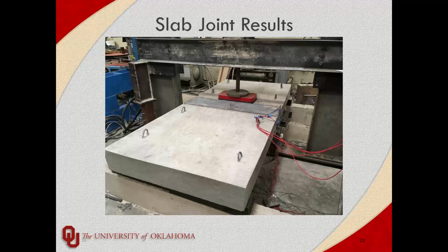And then we did both static tests where we just applied the load until failure. We did 2 slabs of static tests for both materials, and then we did 1 dynamic test where we did about 1 hertz cyclic loading for 3 million cycles. And it was at a load that was just below the cracking load. And then we increased the load to just above the cracking load and took it until it reached a 3/4 inch failure or a 3/4 inch deflection limit. And then after that deflection limit, we tested that slab to failure under static load. Next slide.